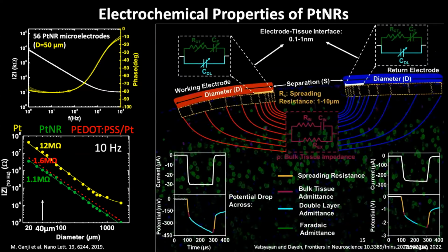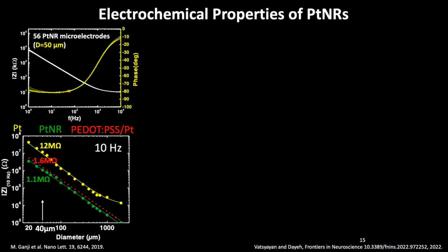And then we have a series resistance, which is mostly current crowding at the edges of the contacts, and then the tissue impedance. And we are concerned with the voltage drops across this interface right here within half a nanometer or so from the contact. There, you want your voltages to be low so that you don't cause electrolysis of water to result in oxygen species or to result in hydrogen bubbles. So we can measure the voltage drop across each of these components and then predict which currents can be safe for stimulation. So how do we do that?